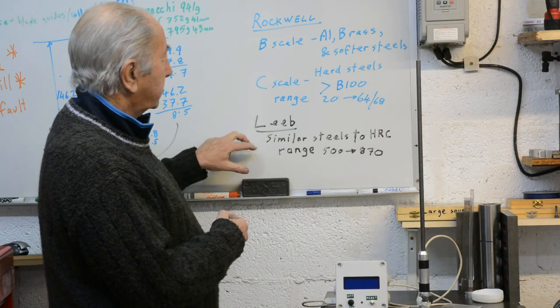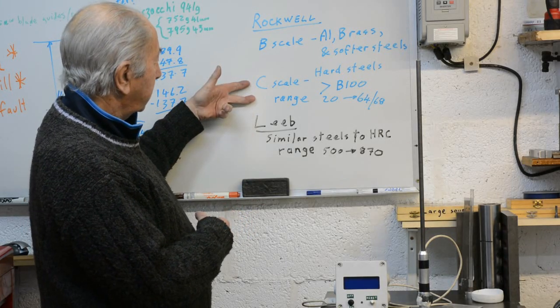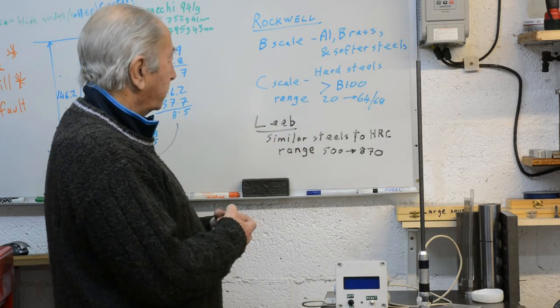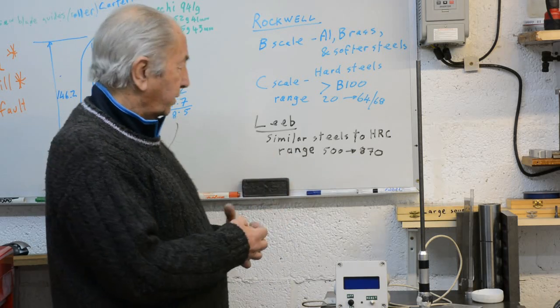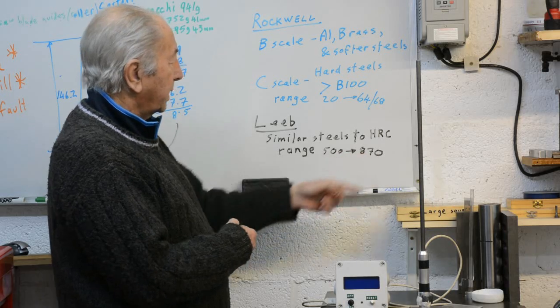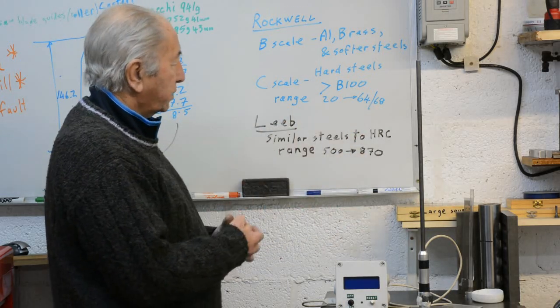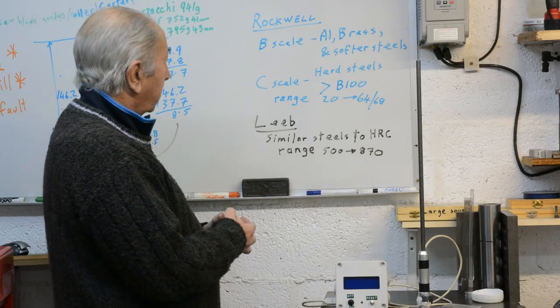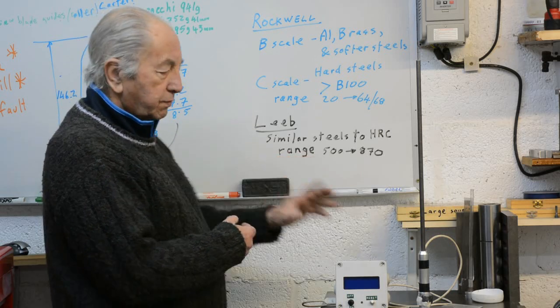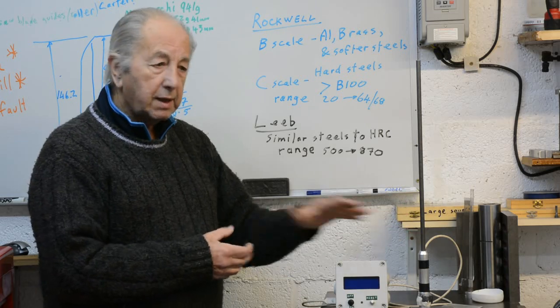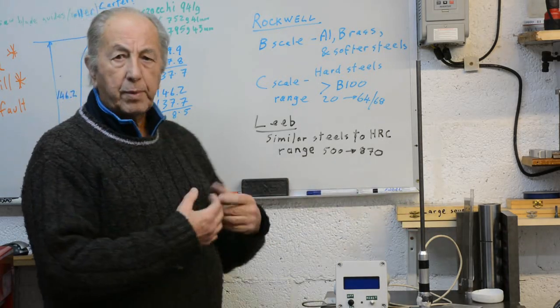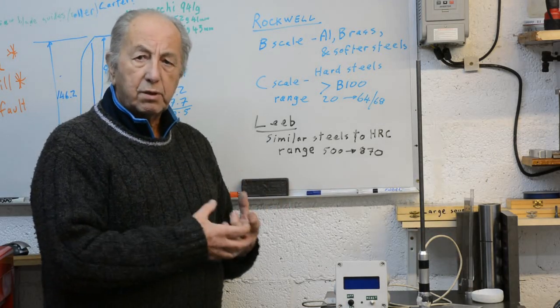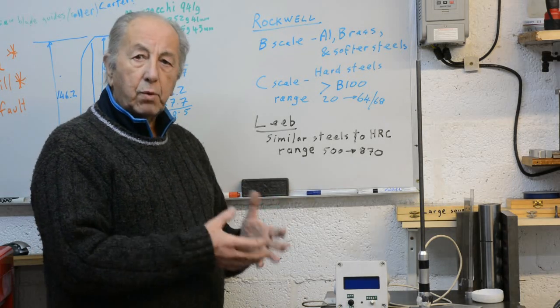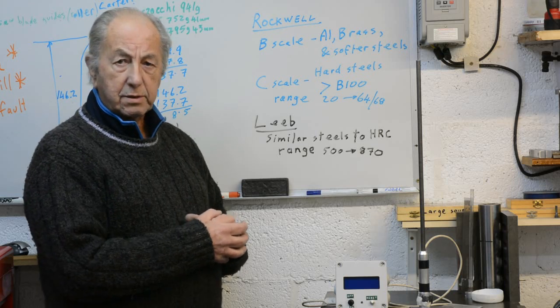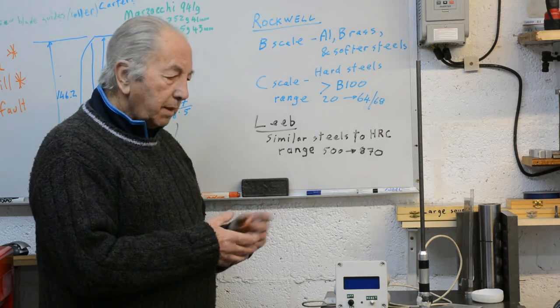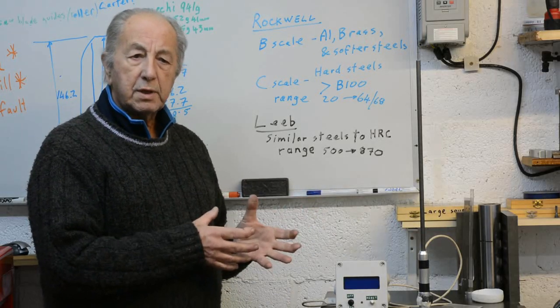With the Leeb, its use is aimed very much like the Rockwell C, in that it's the harder steels, and its range in terms of the numbers it produces is from around about 500 to 870, which converts more or less to the 20 to high 60s. In the C scale, we may well measure things with this, with a rebound tester, like the one I've built here, outside of these ranges. Well, basically all that means is the numbers that we get wouldn't be accepted anywhere that was adhering to the actual hardness standards as set down by various institutions. But it can still give us some useful numbers for most of our purposes.